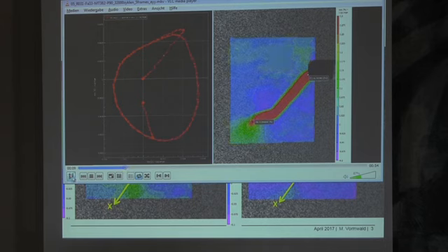if you move this together into such an animation, you see the crack now closes here, and when the normal forces and torsional moments increase, it opens and then it closes again. You see that the closure starts here and propagates to the crack tip. Here's the crack tip, and then it opens again here. Now, the opening proceeds to the crack tip, and ahead of the crack tip are maybe real strains in the material, and behind the crack tip these are these pseudo strains. This is crack opening.